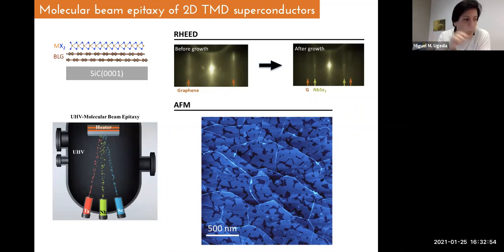Sometimes in the process of the optimization of these TMD materials, we normally take them to AFM to check the cleanliness or the morphology at the larger scales. We also have access to XPS or ARPES machines here in the department. So basically we follow a process of optimization, after which we take it to our STM.